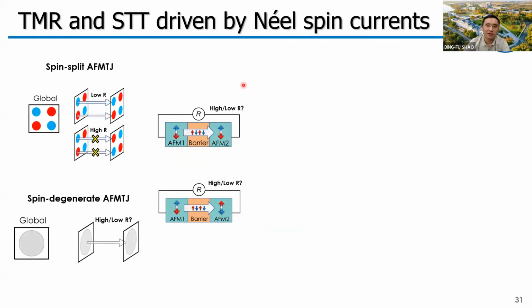The demonstration of the Néel spin currents makes us reconsider the mechanism of the TMR in antiferromagnetic tunnel junctions. Previously, we considered that in order to have a TMR in an antiferromagnetic tunnel junction, the electrodes must have well spin polarized conduction channels.